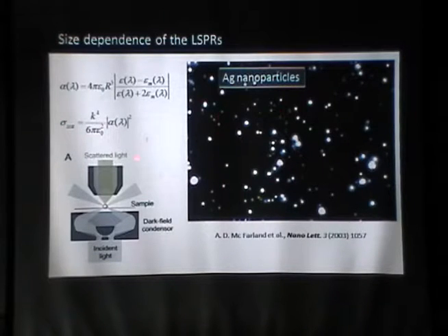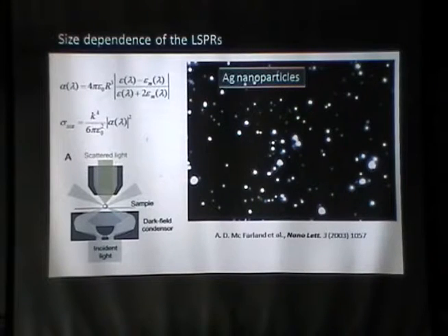So what we are measuring here is scattering of the nanoparticles, and we learned that if we look in the Rayleigh regime, you would say, yeah, it depends on the size, but only the intensity. The resonance condition, which is here, should not depend on the size, right? That's a failure of the Rayleigh regime, because these nanoparticles are larger than 10 nanometers, which would be the limit for the Rayleigh regime. So if we go beyond that limit, the resonance frequency also depends on the size. We'll see that in the next slide, or a couple of slides later.